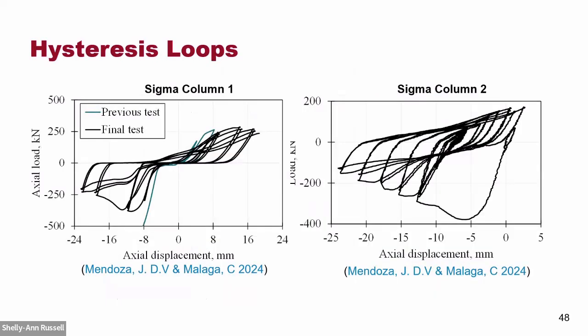So these are the results. This was the sigma column 1 hysteresis loop. You can see there is very little capacity in the tension part because of the connection local damage, and the compression side is stiffer than the tension side. For the second protocol and second sigma column, you can see the behavior is only in compression. For this type of section, we have much more capacity in compression and smoother hysteresis loop curves than this one.